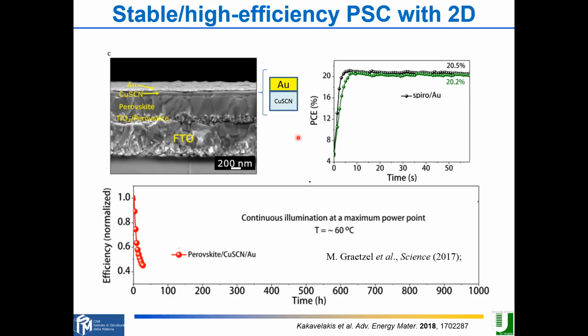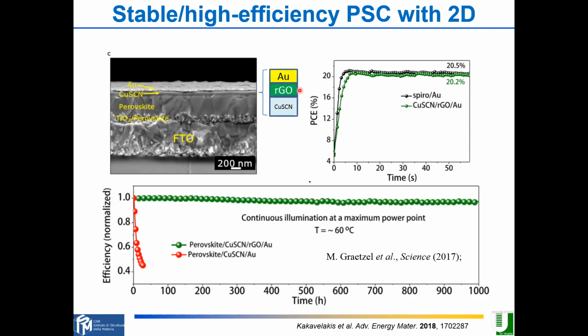If you stress this cell under light soaking at 60 degrees, immediately you have a reduction of the efficiency. This is the efficiency as a function of stressing time, in hours. For a conventional solar cell, you have an immediate reduction of the efficiency, so you degrade the solar cell instantaneously. But if you put a reduced graphene oxide, let's say graphene, at the interface between gold and copper thiocyanate, you immediately stabilize the efficiency of the solar cell.